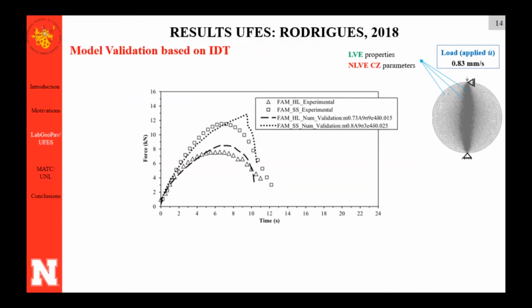So she took the parameters from calibration and she used them as input to simulate an IDT test to validate. Then we observed that the initial slope of the curve, force versus time, the initial slopes were very well determined, and you can see a good match between experimental and numerical. And the mode 1 stress initiation criteria was satisfactory because it also impacts this initial slope.